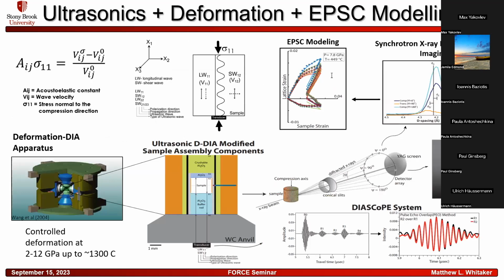And there's a lot going on here, but we basically are trying to determine the acousto-elastic constants of the material. And the longitudinal waves and the shear waves are measured in the sample using ultrasonic interferometry. And then the X-ray diffraction data is collected in addition to the ultrasonic interferometry, and all of this is plugged in through the control system of EPICS, as I mentioned earlier, for the diascope system. The images give the sample length, and then we have the travel times, and the EPSC modeling lets us know a little bit about what's going on in the sample as the deformation continues.